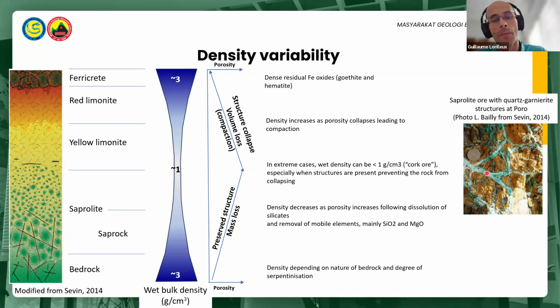In the limonite, all the silicates being dissolved and the porosity collapse, leading to compaction and an increase of the bulk density upward. The upper ferric layer mainly consists of iron oxide or hydroxides, with a wet bulk density also very high, close to around 3 grams per cubic centimeter.